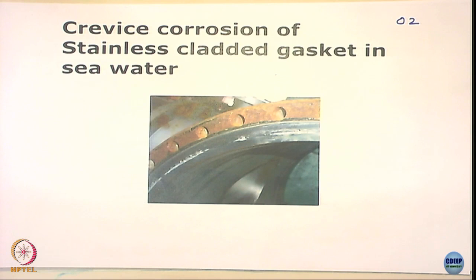So, crevice corrosion normally occurs below the mouth of the crevice, because you need an electrochemical driving force between the cathode and the anode on one hand, and on the other hand the oxygen solubility, the content of oxygen, also decreases as you move from the mouth of the crevice to the center of the crevice. So, that is how you see that crevice corrosion always occurs below the mouth of the crevice. I hope you understand, and this one is very important actually, okay.